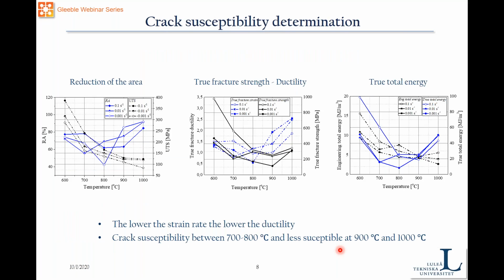The crack susceptibility results look like this. By comparing the reduction of area method together with the true fracture strength ductility and the true total energy, we could obtain this type of results. Maybe this can be a bit confusing now, but I will help you by highlighting that there is a range of temperature in which we can see something is happening in the material. Starting from the reduction of area, there is a point where we can see that it is changing, the ductility is dropping.